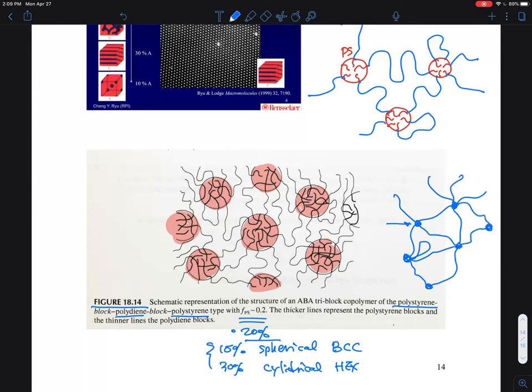It is a network polymers. I cannot draw the infinite network structure, but it looks like a network structure. This domain has just a Tg around 100 degrees C. So if you heat it above the Tg, let's say up to temperature 120, 130 degrees C, this whole thing is softened up, and then it behaves like just any other thermoplastic polymer. You can injection mold it.